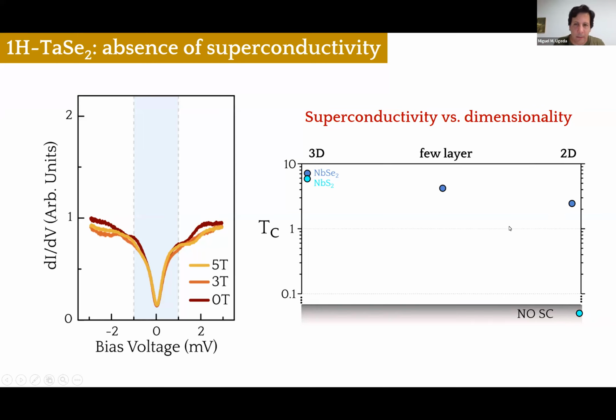For the case of tantalum-based TMD materials, the behavior is actually disparate. For tantalum disulfide, it has been reported an increase of the critical temperature, a reinforcement of superconductivity with the number of layers. Whereas for tantalum diselenide, it shows the opposite trend. So this superconductivity disappears as well, at least at 300 millikelvin. So these trends are not clear, or there is no picture that explains this disparate behavior in this family of materials.